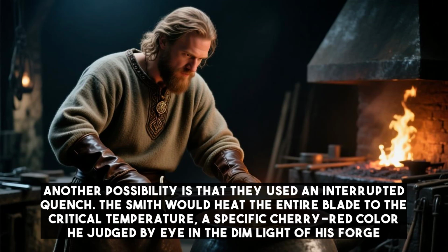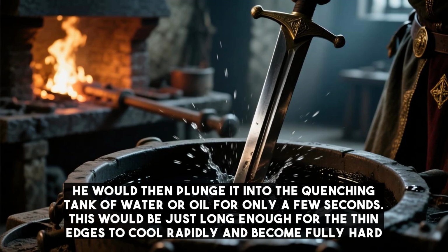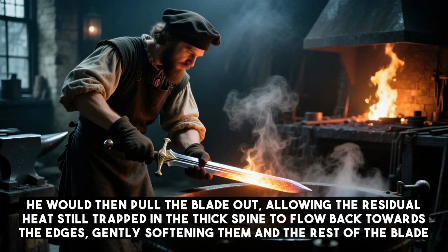Another possibility is that they used an interrupted quench. The smith would heat the entire blade to the critical temperature, a specific cherry red color he judged by eye in the dim light of his forge. He would then plunge it into the quenching tank of water or oil for only a few seconds. This would be just long enough for the thin edges to cool rapidly and become fully hard. He would then pull the blade out, allowing the residual heat, still trapped in the thick spine, to flow back towards the edges, gently softening them and the rest of the blade.